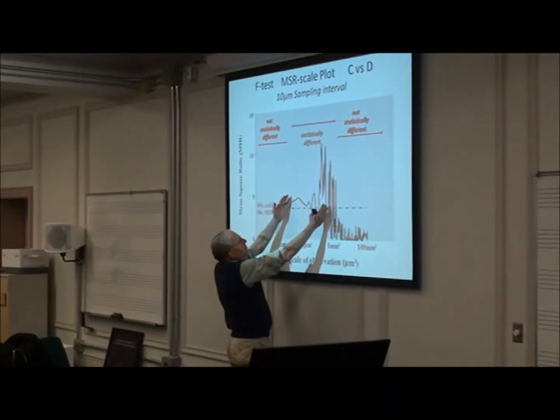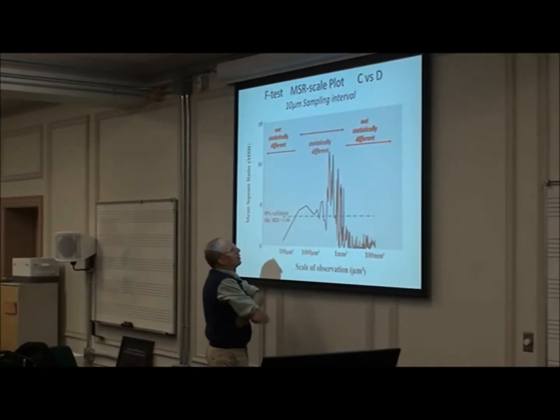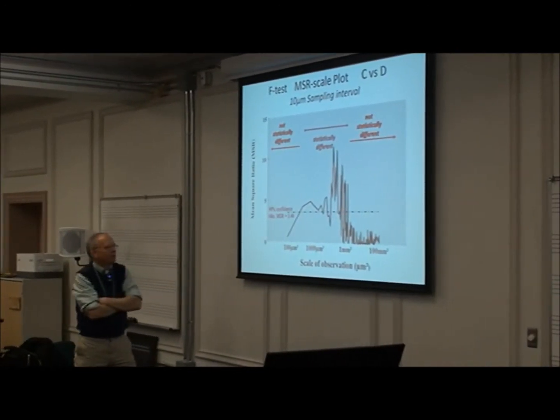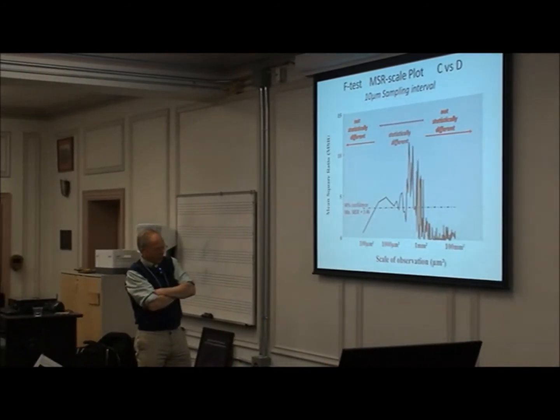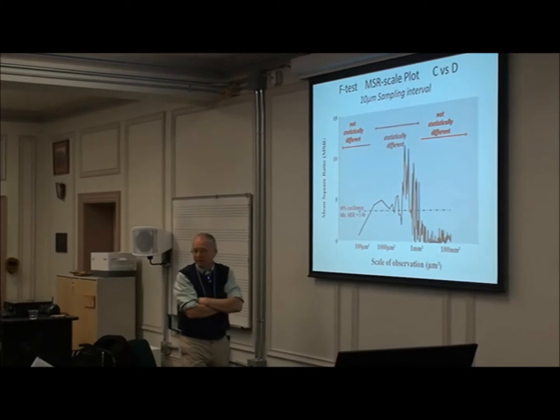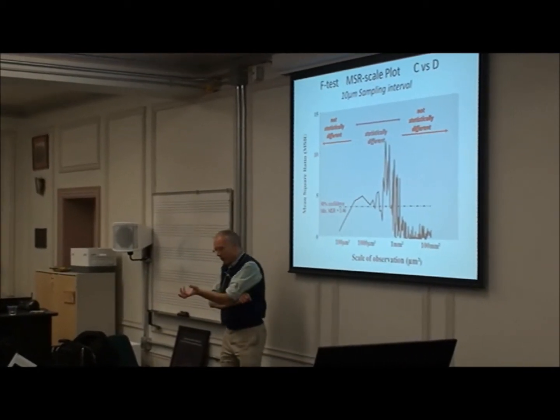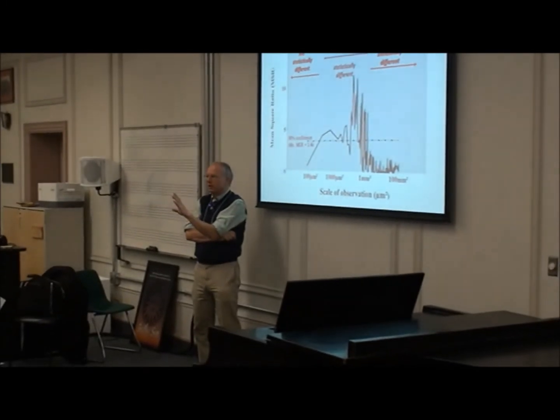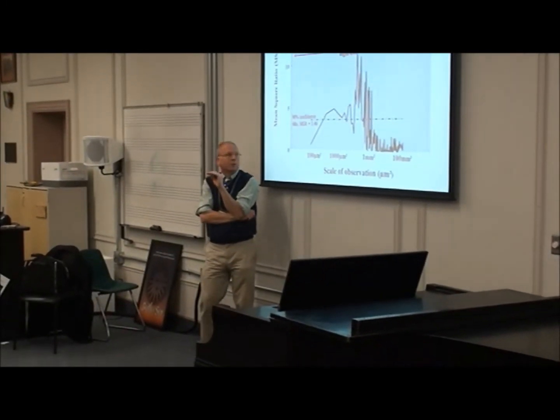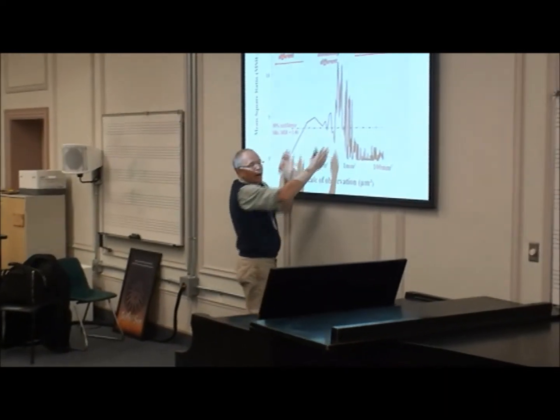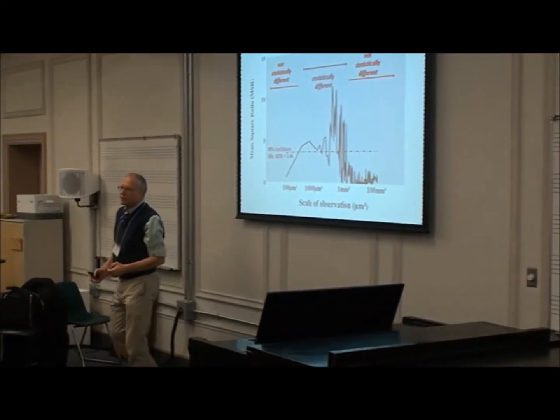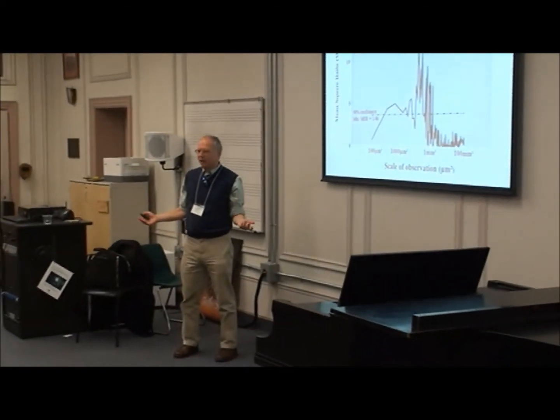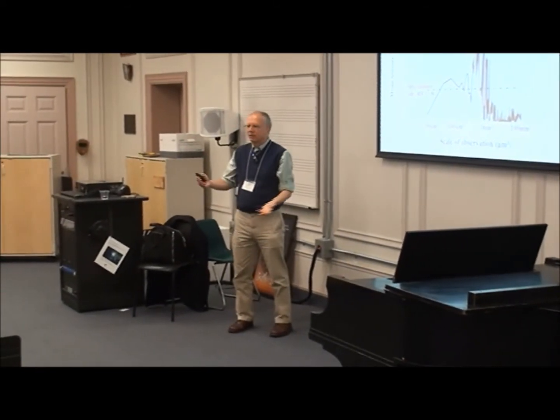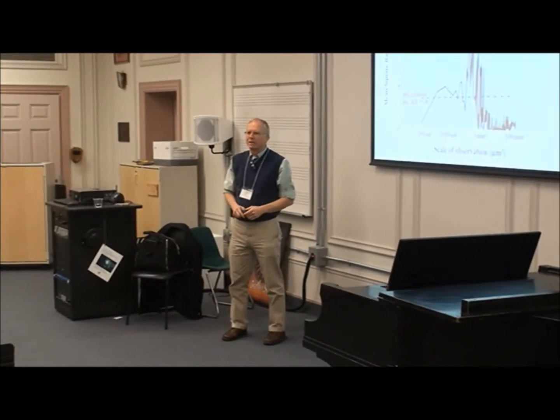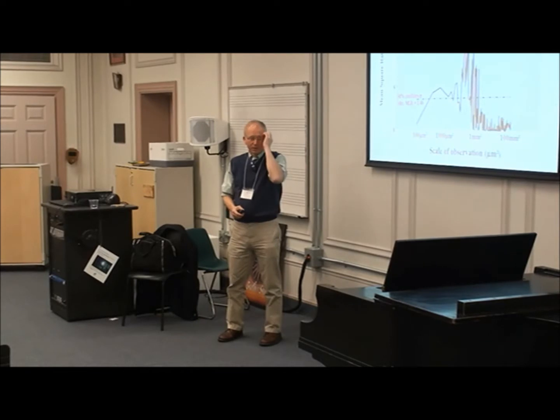So over that range approximately, we're about 90% confident we can tell the difference. If we believe that, and we go out and test those skis, then that would mean that the scale of interaction where the snow and the melt layer, a very complicated kind of friction situation, interacts with the ski is in that range, if those skis behave differently on the snow. That turns out to be a really difficult thing to figure out, because every run down the snow is different and every skier is different. I've had two different pairs of skis. The skis are different. So it's a pretty hard test to do to see which one is really better.